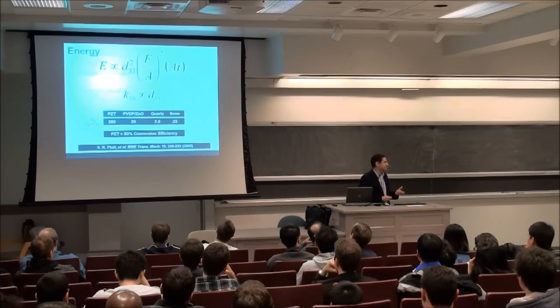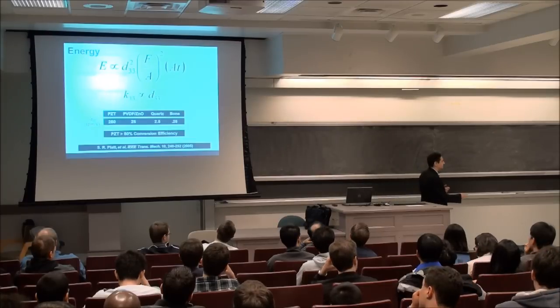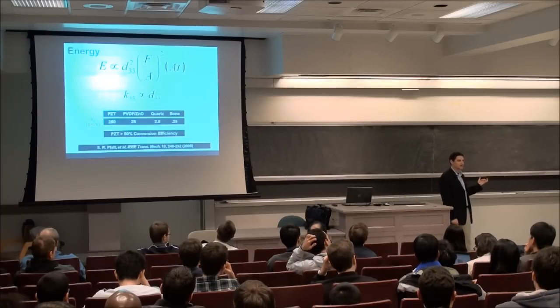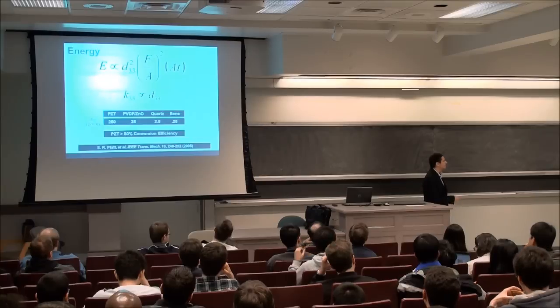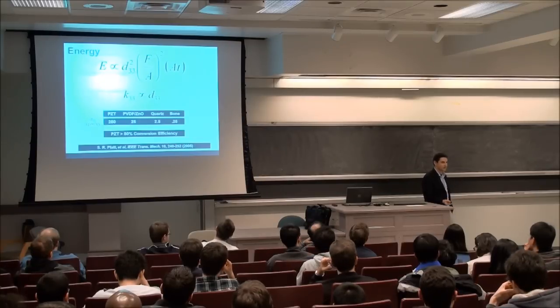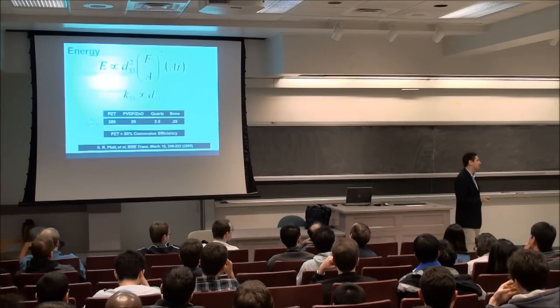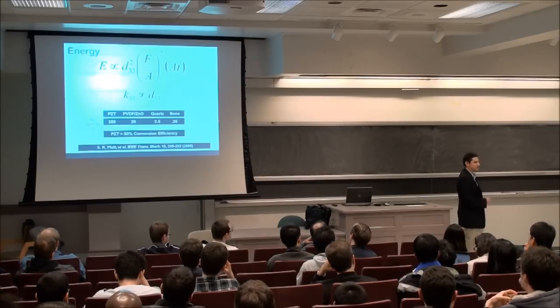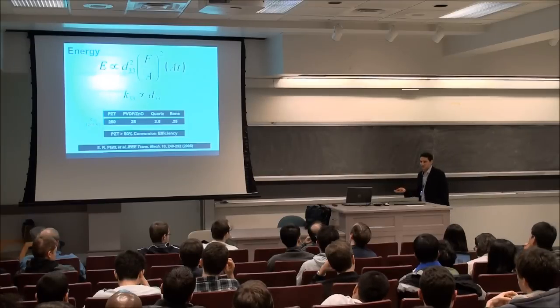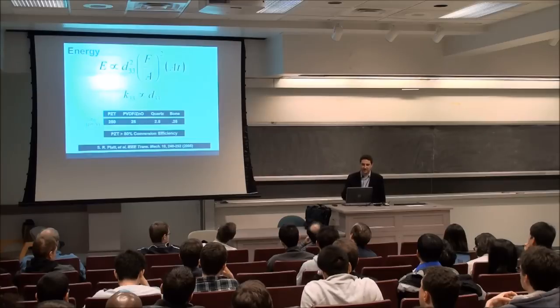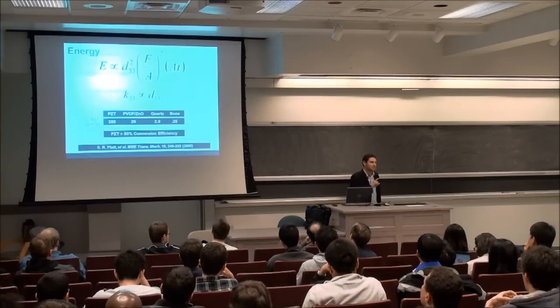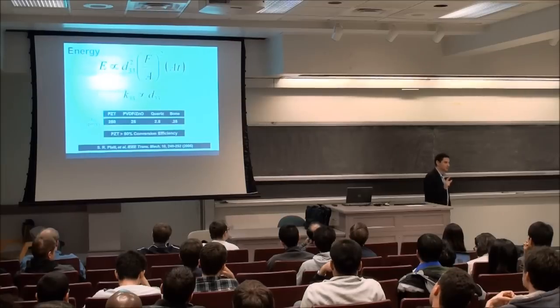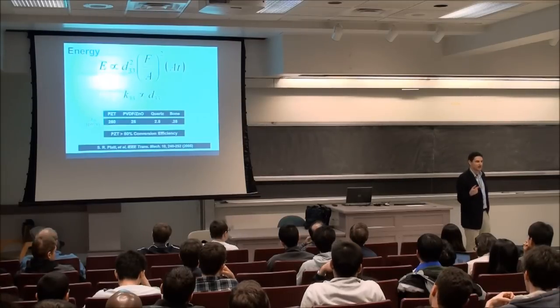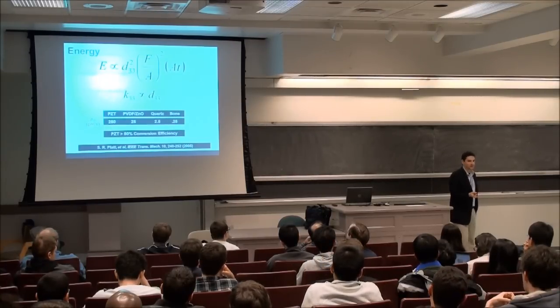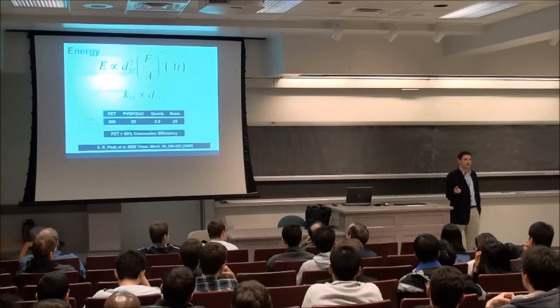But the one material that is, PZT, actually has a piezoelectric charge constant about 10 times that of zinc oxide and PVDF. So it's 10 times more efficient at converting power between electrical energy and mechanical energy. In fact, it can be up to 30% efficient. So if one wants to create an energy harvesting system, it seems like the perfect material to use, but of course it's a hard, brittle material, and it has lead in it, which is not biocompatible. So there are some problems there too, and this is where we use nanotechnology to get around that.